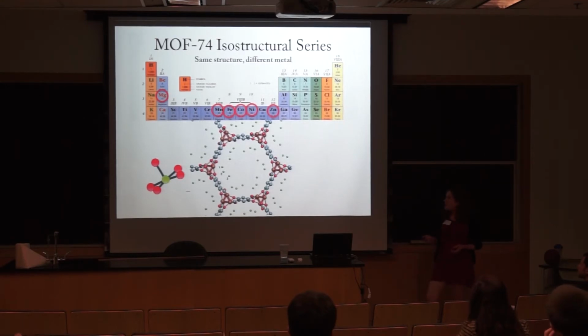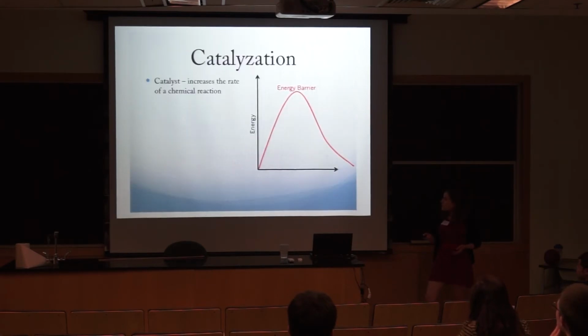of metal. The special thing about MOF74 is it has this open metal site. So you have your metal here in green, it's bonded to 5 other atoms, and it really wants to bond to 6. So this gives it a higher binding energy, around 10 kilojoules per mole, instead of like 5 for other MOFs. So what is catalyzation?